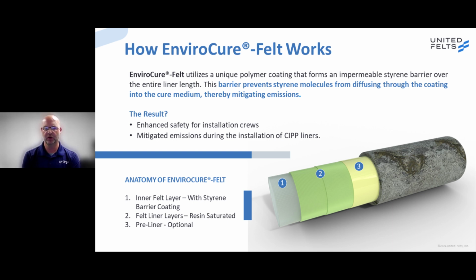So the steam plume, which was identified in some of the previous studies as having high potential styrene emissions, this EnviroCure coating keeps styrene from the steam plume as well as the cure water for water inversions and hot water curing.